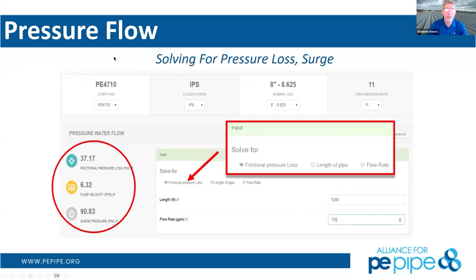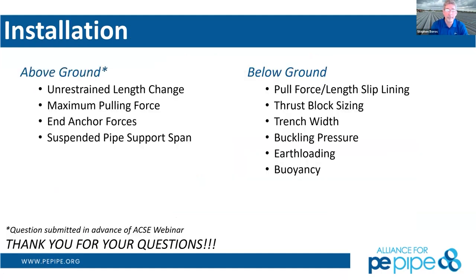So you go to the HDPE app. Let's say I'm going to solve for frictional pressure loss. And I'm going to see, okay, at a mile of it, at 750 gallons per minute, I'm going to have a frictional loss of 37 PSI and a fluid velocity of 6.3 feet per second. That's well within the design window of polyethylene pipe. So you're not going to have any problems there. You can even go up to 12 feet per second with polyethylene pipe and not have any issues based on surge. Real key aspects. You can play with all these different ways of solving that.